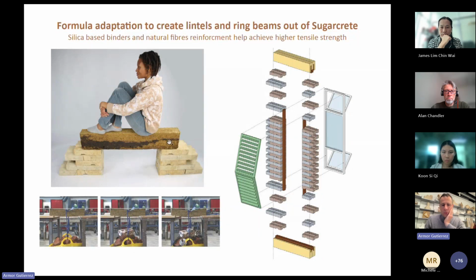And we managed to achieve an improvement in the resistance of these lintels. First we tested including a timber element in the middle, and we also tested including a Hessian mesh on the underside, where the Hessian mesh alone increased the loading capacity three times compared to just the version with the Sugarcrete lintel. We designed this as the window opening, so we could have a lintel at the top, a lintel at the bottom, and then just resolve it with blocks without any wastage, because we wouldn't need to cut any of them, just by using the regular block and the oversized one.